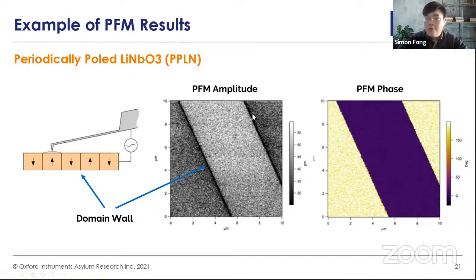On the left side, we have the PFM amplitude image. What I want to explain is that these dark lines, the boundaries here, are clearly seen, and they are actually the domain walls. The reason is that when we scan at the domain wall, the piezo responses from the adjacent domains cancel out each other. Therefore, the motion or the amplitude at this domain wall is very small, basically at the lowest value you can measure in the amplitude image.